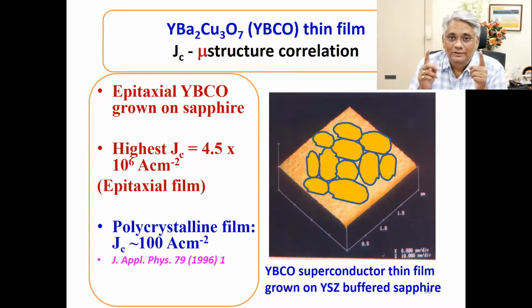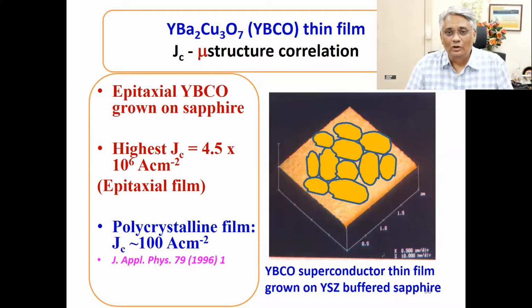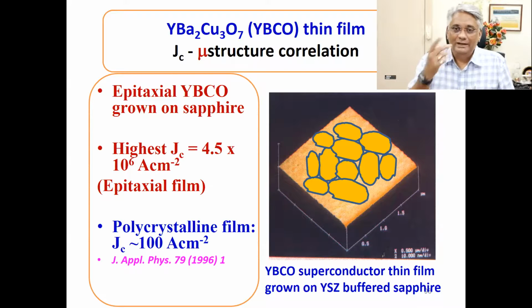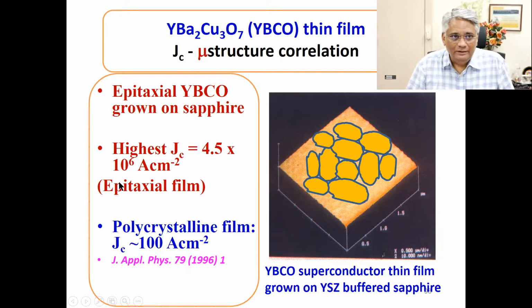So these wires have to have a certain amount of current carrying capability, and so the current density rating is normally anywhere from 10⁴ to 10⁵ amperes per centimeter square, because these are the normal metallic wires, right? But if these wires are made of superconducting wires or tapes, then the current carrying capability should be as high as 10⁶ amperes per centimeter square, almost 2 orders more, right?